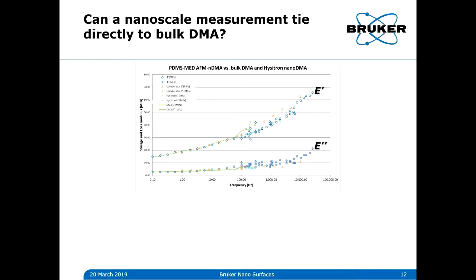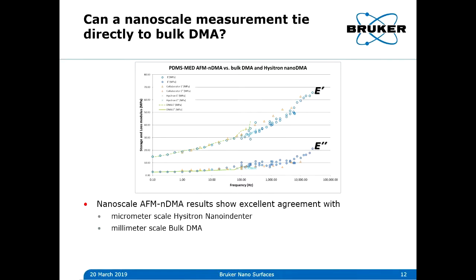So how does the AFM compare to bulk DMA? Well, we compared our results on PDMS, and we found that we are getting excellent agreement with both the Hysitron nanoindenter, which is shown here in blue crosses in the center, and with the bulk DMA machine, which is the green lines, and this is storage modulus and loss modulus down below.